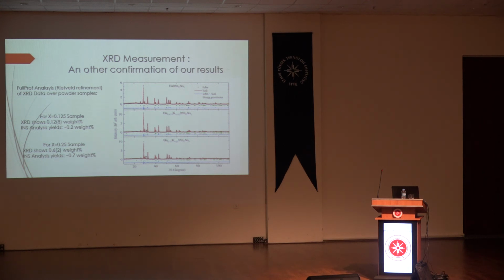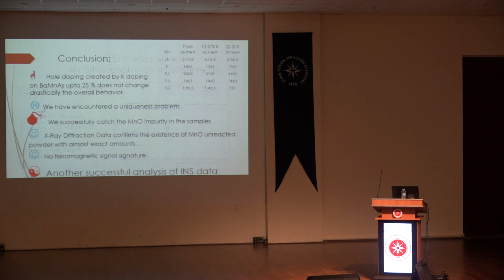When we tried to publish the data 6 months ago, the referee asked us, you have to put this data, otherwise you cannot publish, he doesn't like it without that. And Pandev, my friend over there in Ames, did the XRD experiment, and when we fit, this is pure, it is 12%, it is 25%, as you see, the intensity increases. The intensity ratio is exactly the same intensity ratio that I got from my inelastic scattering analysis. And that is the whole conclusion.